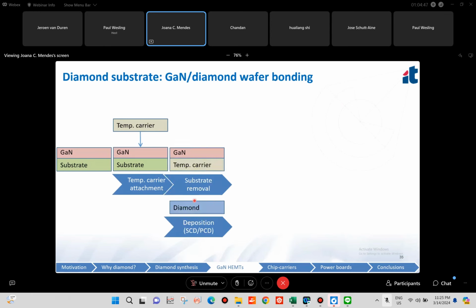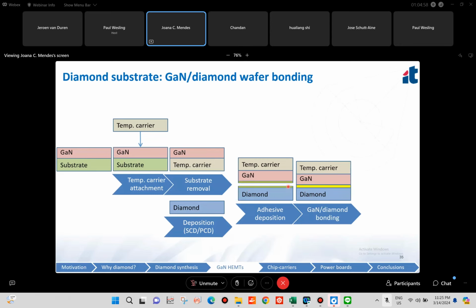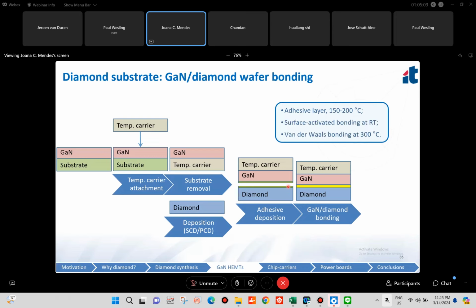And then we just take a diamond crystal, whether single crystal diamond or polycrystalline diamond, and we may deposit an adhesive layer on both wafers, and then we just bond them together. We can do it through thermocompression at moderate temperatures between 150 to 200 degrees C. We can use surface activated bonding at room temperature or van der Waals bonding at 300 degrees C. And of course, in the end, we just remove the temporary carrier, and again, we have a GaN on diamond wafer.